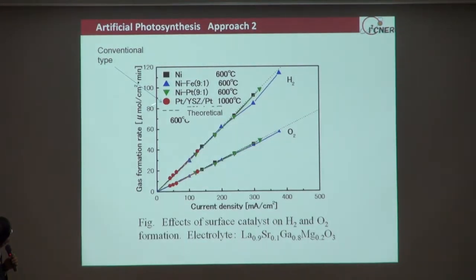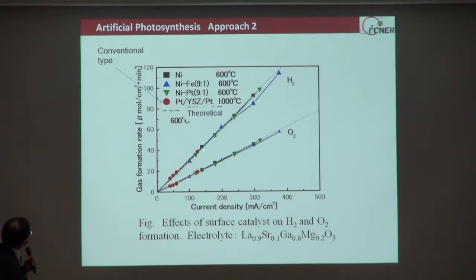And this is the result obtained previously by using the lanthanum gallate. And this is the conventional cell. In the conventional cells, we use yttrium-stabilized zirconia for the electrolyte. And this is the case of platinum used for the electrode. We observed hydrogen and oxygen very close to the theoretical Faraday's law. But compared to the conventional cells, although the operation temperature is 400 degrees Celsius lower, by using, for example, this electrode, we can obtain more than 3 times larger amount of hydrogen